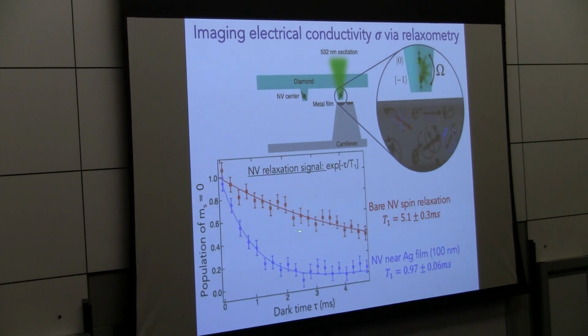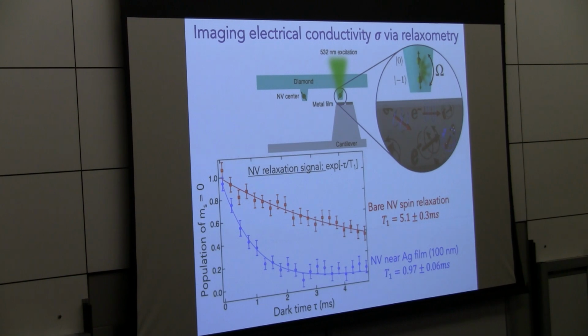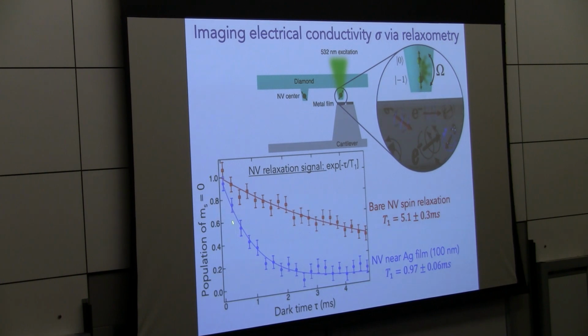For an NV far from the conducting sample, we get a T1 of about 5 milliseconds. This is typical for NV centers at room temperature. And then we bring the NV center nearby the conductor, in this case a silver film, and the T1 went down by a factor of a few.